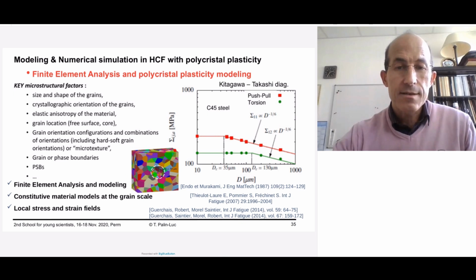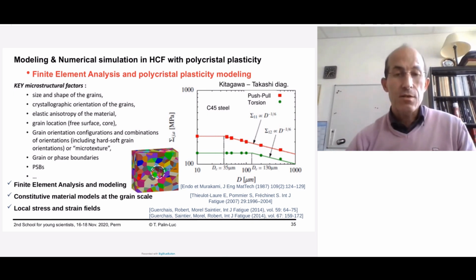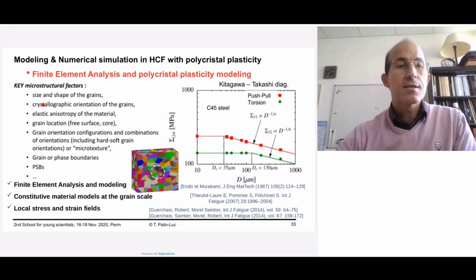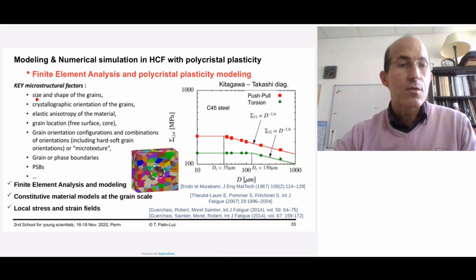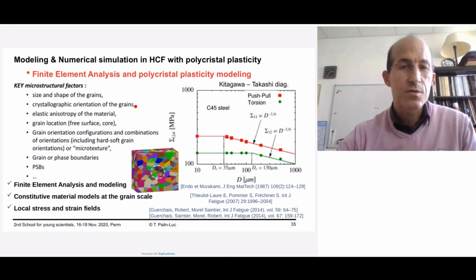The typical size here is a few hundred micrometers, and each color here represents one grain. It means one crystal with its own crystallographic orientation, its own slip systems, elastic behavior, but also elasto-viscoplastic behavior. And the challenge is to take into account the effect of the grain size and shape, the crystallographic orientation of the grain, as I explained, the anisotropy of the grain, the effect of the surface